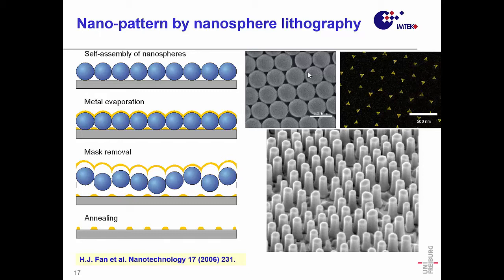By changing to different sizes, you change the space in between. So you spread them in a spin-on-glass process or a sedimenting process on your wafer. Then you do an evaporation through these holes. You get what you see here on the left-hand side, this gold pattern. You remove the spheres, if it's polystyrene, simply chemically, and then you have this gold pattern.